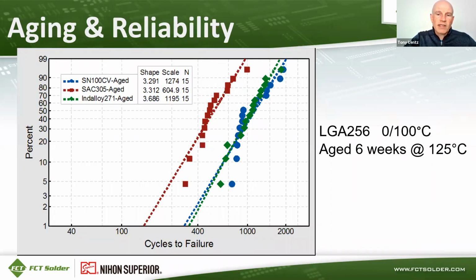Here's that same data set, but after aging 6 weeks at 125C. SAC305 is again the lowest life alloy in this test. And then you've got SN100CV and Indalloy matching each other. So their lives overlapped after aging.